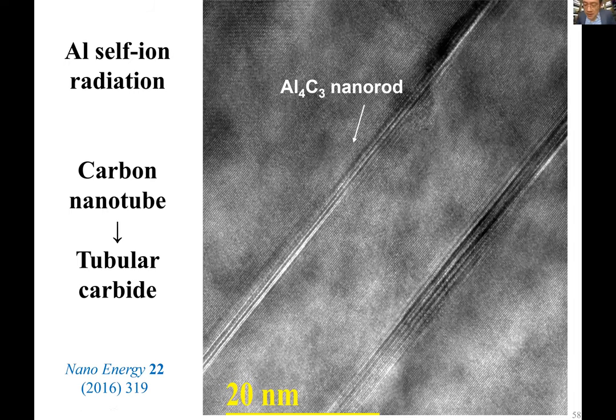Now there is a lot of radiation mixing when you do 72 dpa. So that basically means every carbon and every aluminum atom is knocked out from their original site 72 times. And so after much radiation, actually the carbon nanotube is chemically gone, but it's kind of like a fossil record. So it's a rock, no longer organic, but the morphology is maintained. So we see this very long straight aluminum 4 carbide in the post-radiated material, and it still sort of maintains these interfaces. And this is important because generally we know that nanostructures, their interfaces provide venues for radiation vacancies and interstitials to recombine.